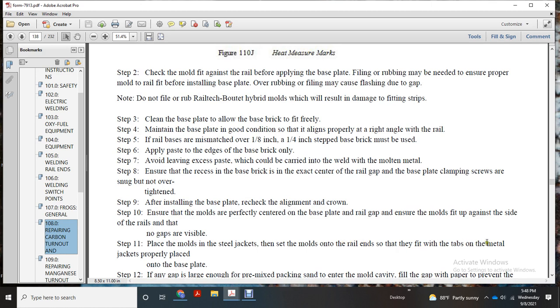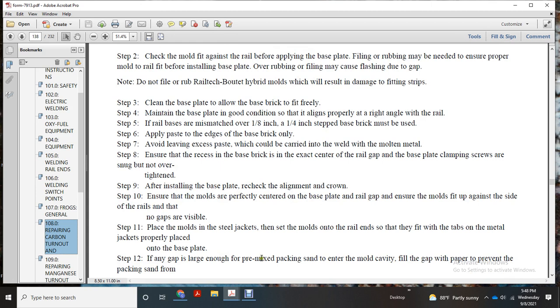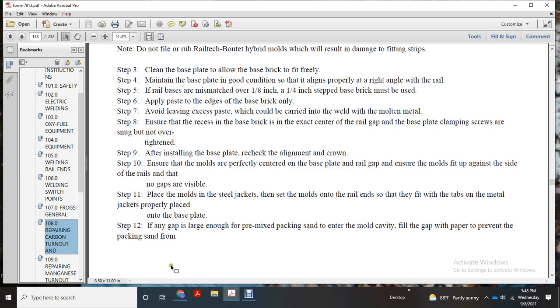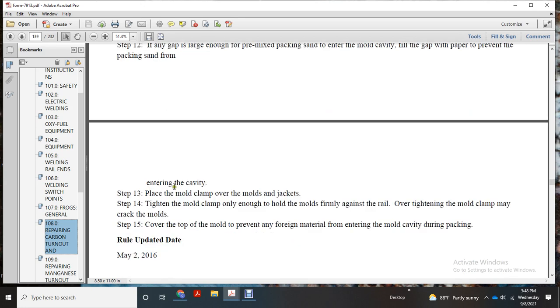Then fit them with the tabs on the metal jackets properly placed onto the base plate. If any gap is large enough for the premixed packing sand to enter the mold cavity, fill the gap with paper to prevent the packing sand from entering the cavity. Place the mold clamp over the molds and jackets.